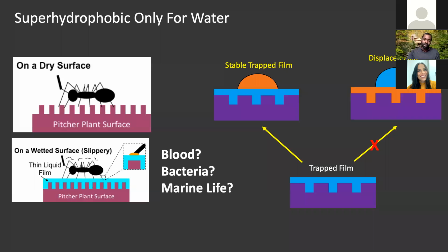And with some other liquids, let's say it's oil, you really have to start playing with the energies of the system that you're designing to make sure that you're able to trap your desired film, and the underlying surface should repel the thing that is not desired. And if you don't match this properly, let's say the thing that you want to repel likes the surface more than the water does, or whatever liquid you trap, then it can displace that liquid, and essentially you get pinning, and it's even worse than if you didn't do anything.